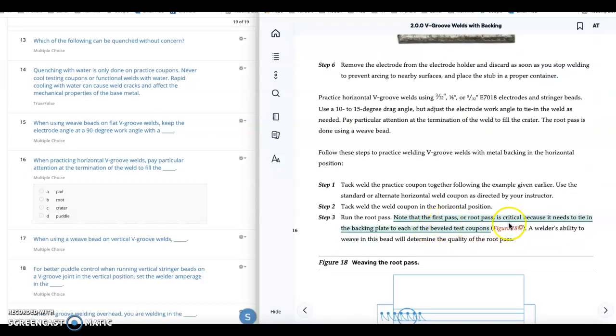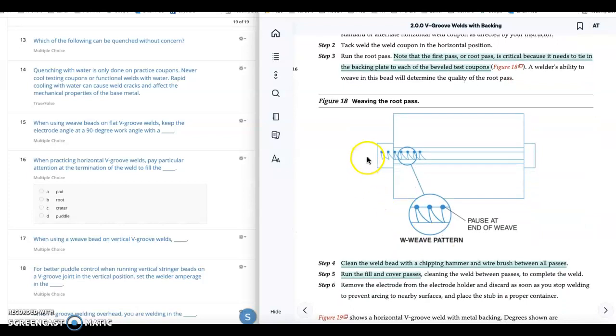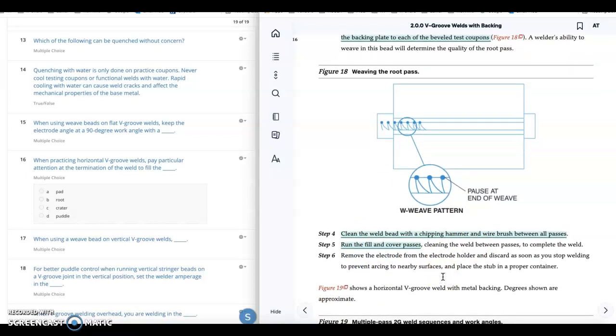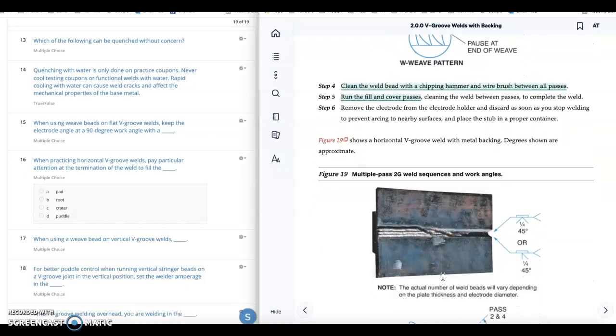Note that the first pass, the root pass, is critical because it needs to tie into the backing plate of each bevel test coupon. Weaving a root, a W weave. You can see how they do little W's. You want to pause at the end of each weave. Clean the weld bead with a chipping hammer and wire brush between all passes. Run the fill and cover passes.